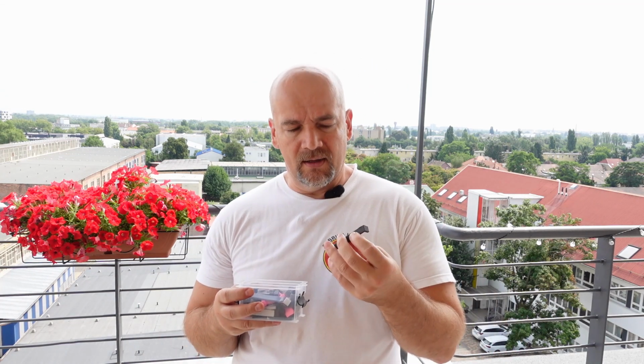And carbon. Interesting, but I have to experiment a little bit more with this to find a solution, what are the optimum settings to get a little bit better quality of the printing, a little less stringing. And yes, it is very strong, but don't forget those carbon fibers are oriented in the direction of the printing. So for example, in tensile strength it is much stronger, or in bending test, but it is not so strong in the layer adhesion test.